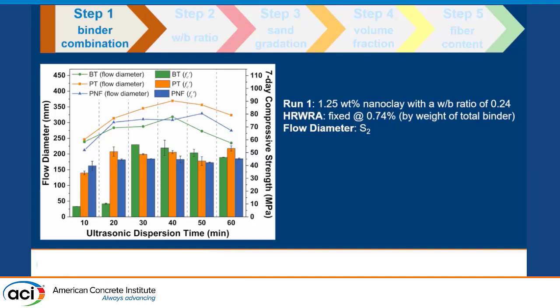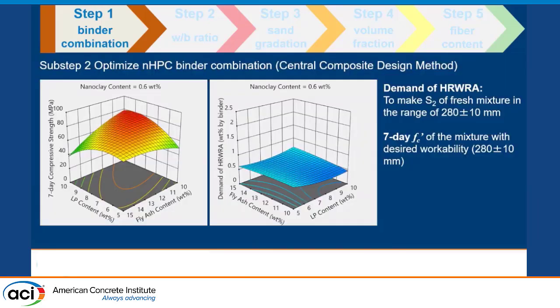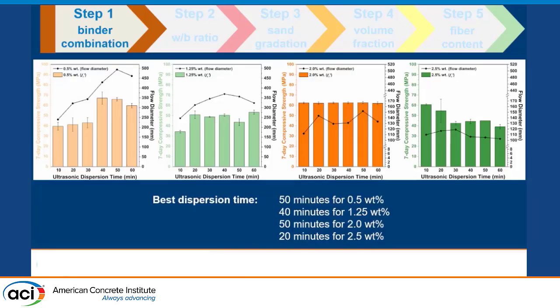We investigated 3 types of nanoclay, and as you can see from the results on the left-hand side, we will select the PT nanoclay. The best dispersion time is 40 minutes for the nanoclay content of 1.25%. If you remember, we have four nanoclay contents, so we can similarly do the same test to obtain the best dispersion time for each content of nanoclay.